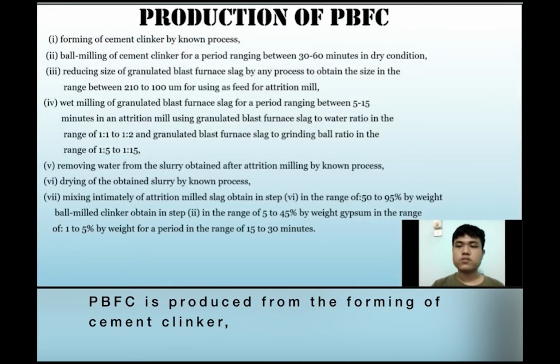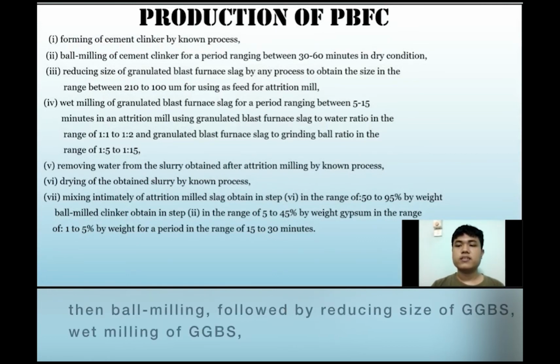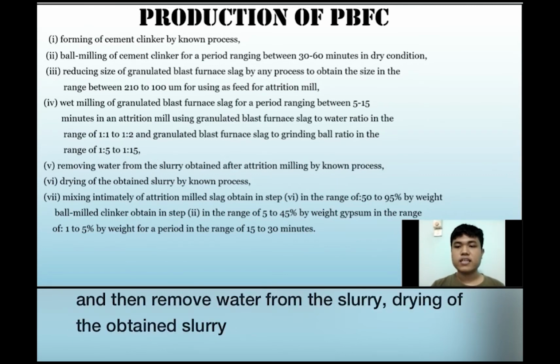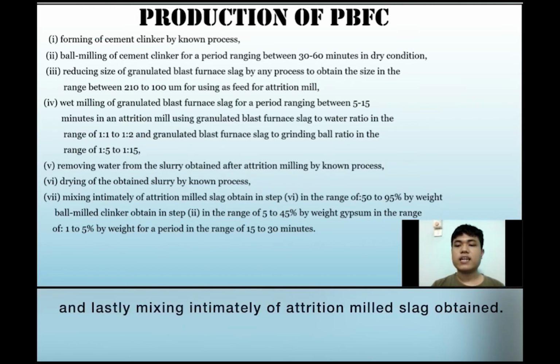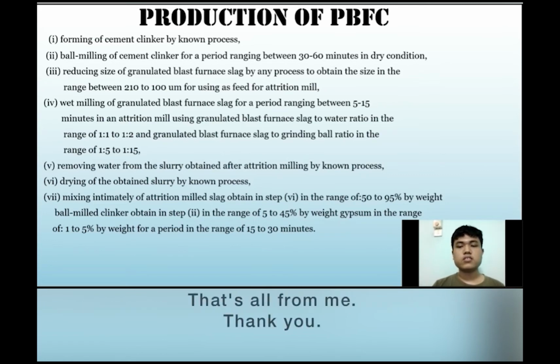PBFC is produced from the forming of cement clinker, then ball milling, followed by reducing the size of GGBS, wet milling of GGBS, and then removing water from the slurry, drying of the obtained slurry, and lastly mixing intimately the attrition mill slag obtained. That's all from me.